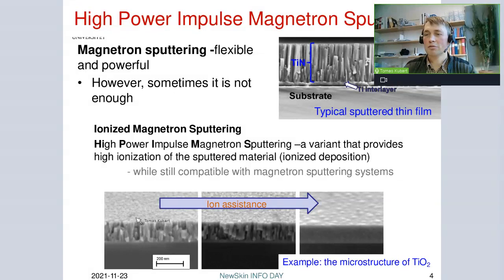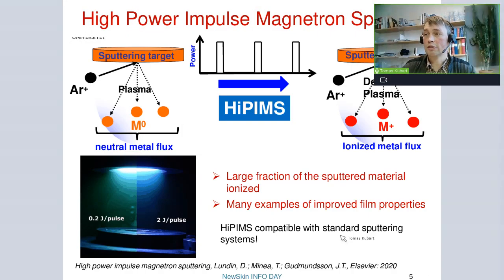And here is an example of, for instance, a titanium oxide thin film, where by changing the growth conditions, we can go from a columnar to a very dense and featureless microstructure. This is very useful in many cases. I will not talk about the technology as such. I will just mention that this technology is compatible with magnetron sputtering. So if you know magnetron sputtering, you can do high power impulse magnetron sputtering too. It's just that the way the plasma or discharge is created is different, but otherwise the hardware is the same.